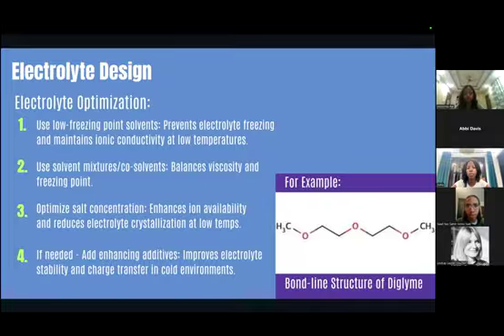And secondly, solvent mixtures and co-solvents are a possible solution because by combining multiple solvents with different properties, the electrolyte can achieve an optimal balance between viscosity and freezing resistance. And this precise formulation can ensure ions can move efficiently even as temperature drops. Thirdly, salt concentration requires careful optimization because the exact concentration of salt determines both ion availability and solution stability. For example, too much salt can risk crystallization in cold conditions, while too little reduces conductivity. And the optimal concentration maintains high ionic conductivity while preventing unwanted crystallization at low temperature.